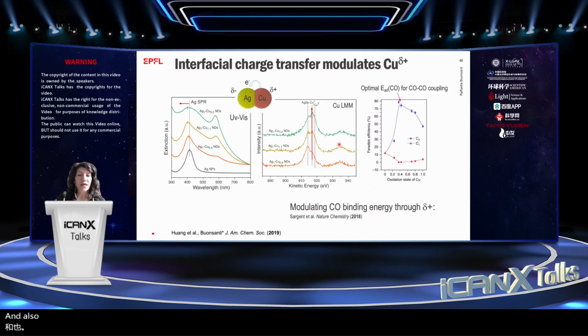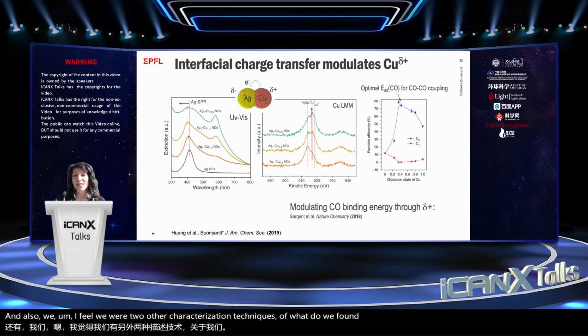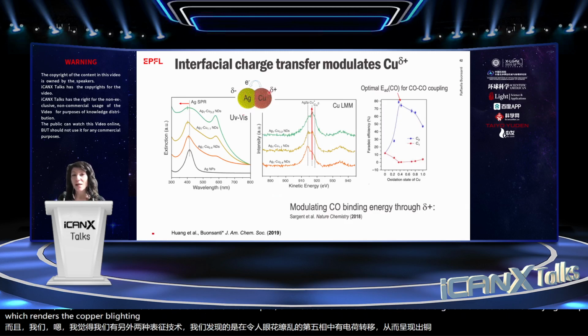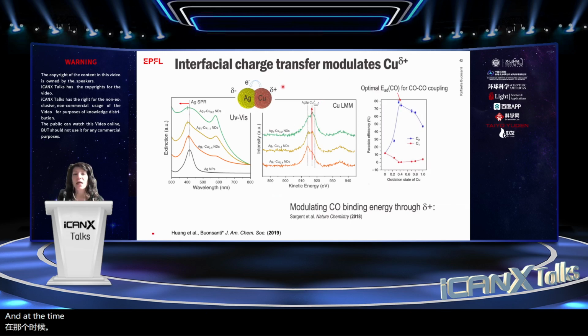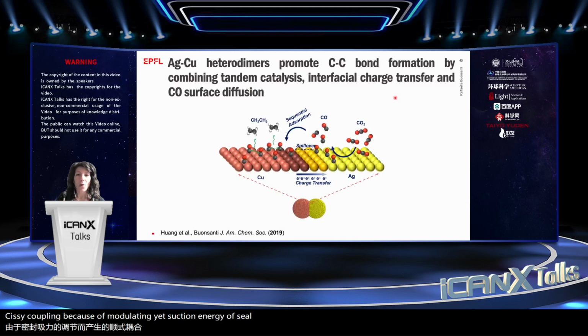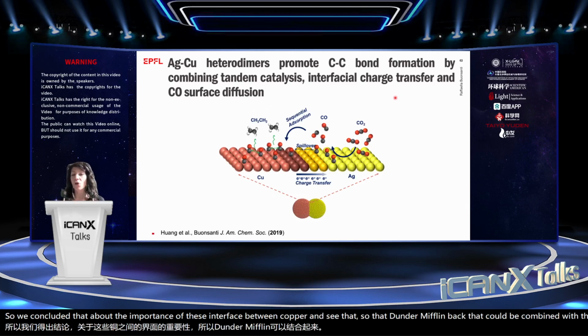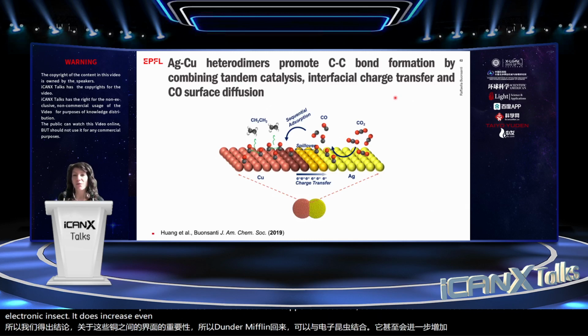And also, through other characterization techniques, what we found is that there is a charge transfer across this interface, which renders the copper slightly positively charged. And at the time, this slightly positively charged copper was believed to improve the CC coupling because of modulating the adsorption energy of CO. So we concluded about the importance of this interface between copper and silver, so that the tandem effect could be combined with the electronic effect and thus increase even further the CC coupling.